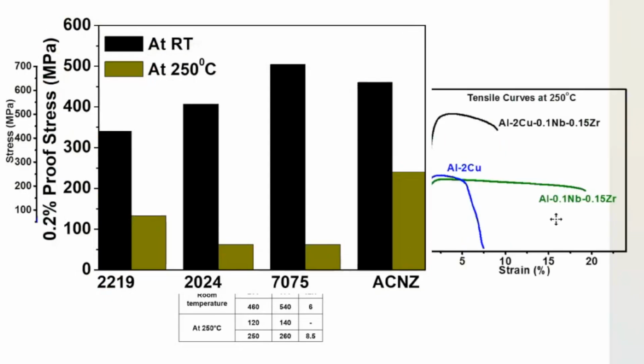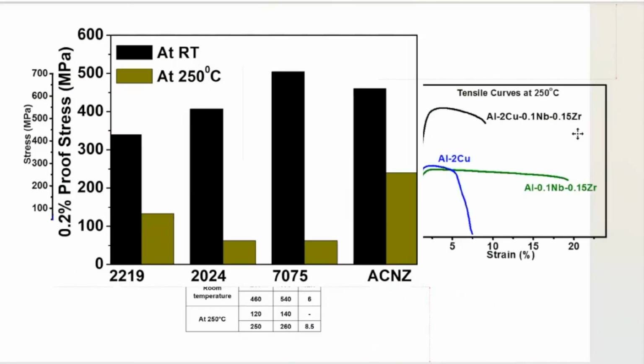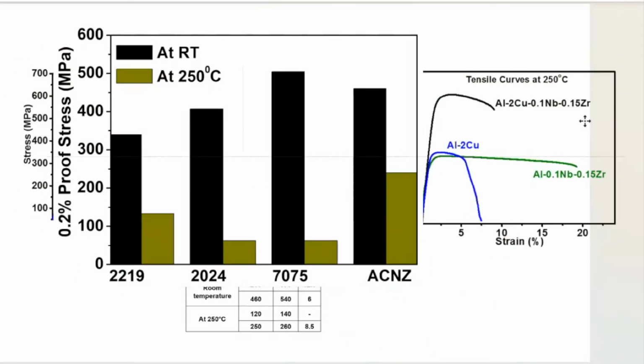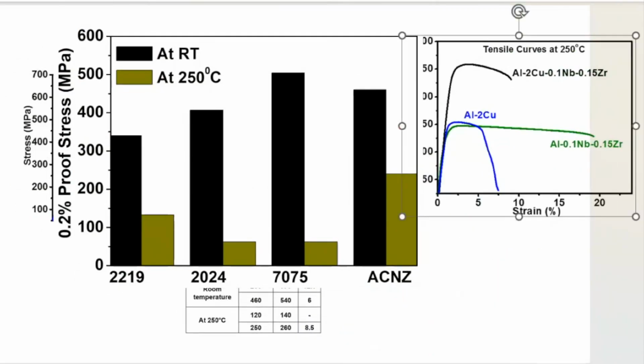I think I should show this stress strain diagram. Hopefully, you can see a part of it. You can see that the tensile strength of aluminum copper niobium zirconium is very high, whereas aluminum copper hardened is much, much lower at 250 degrees centigrade.